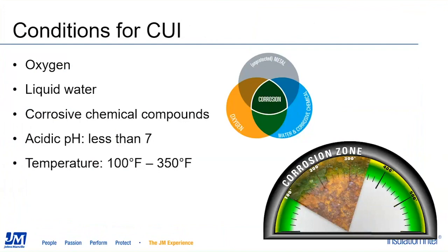For corrosion to occur, you actually need a combination of conditions to be present. Those conditions are the presence of oxygen and the presence of liquid water. While water vapor itself will not create corrosion, it doesn't take much for the water vapor that gets into an insulation system to turn into the liquid form. So if you do have significant water vapor ingress in your system, you do have the potential for corrosion to occur anyway, because it's very likely that it will turn into liquid water.